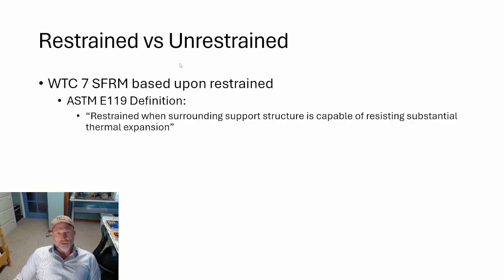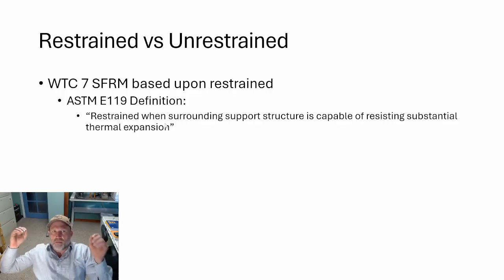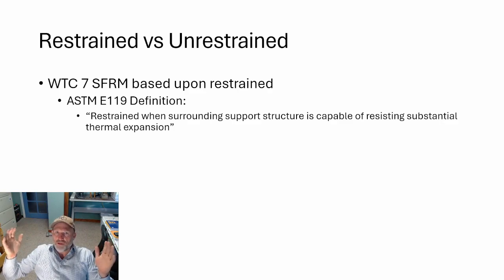So let's talk really quick about restrained versus unrestrained. This is interesting because the definition from ASTM E119 for restrained is that when it's surrounded by a support structure that's capable of resisting substantial thermal expansion. And the reason that's important is the amount of fire resistant material, the thickness, is going to be different for a restrained member versus an unrestrained member. That has to do with the thermal expansion. You need more in an unrestrained member to make sure that during thermal expansion, you're not going to lose that fire rated material.